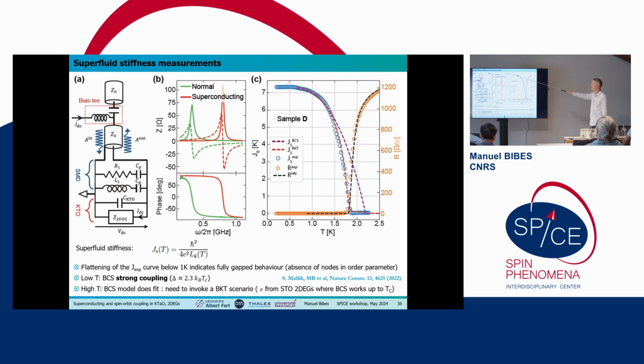And at low temperature, the scaling suggests a possible strong coupling, okay? But there's a deviation. If we go to higher temperatures, there's a deviation. The pure BCS strong coupling fit doesn't work, and we need to go to a BKT scenario to be able to fit properly the JS dependence with temperature together with the dependence of the resistance with temperature.